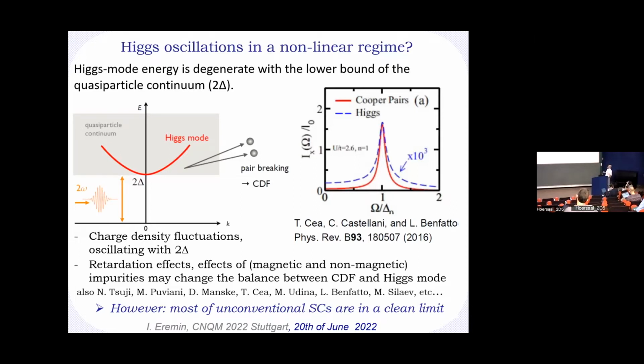It turns out that the Bogoliubov quasi-particles produce very similar features in the third harmonic generation, except three orders of magnitude higher than the contribution from the Higgs mode. This is not surprising, because even in the linear response the coupling is weak, so even in the nonlinear response the coupling to the Higgs fluctuation is still quite weak. This basically tells you that the signatures you are very likely seeing in the nonlinear response, in the pump probe generation as well as in the third harmonic generation, are a response associated with Bogoliubov quasi-particles.